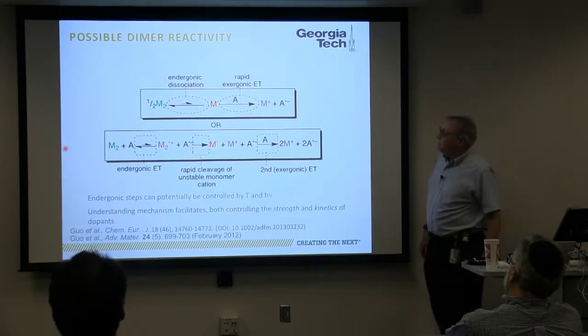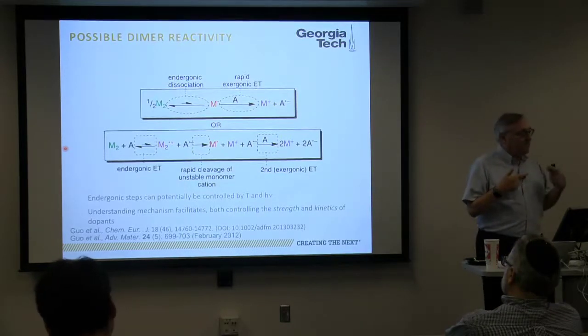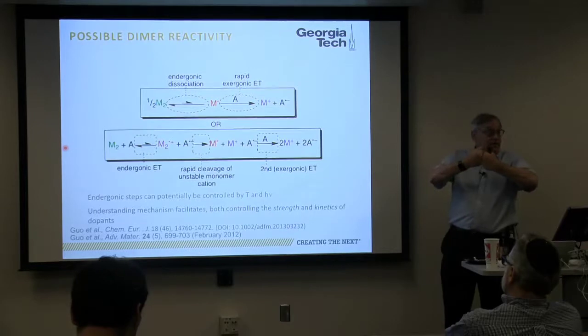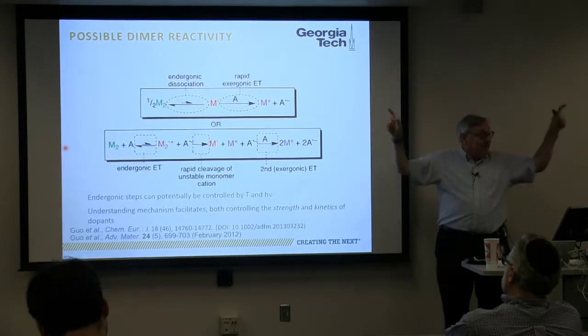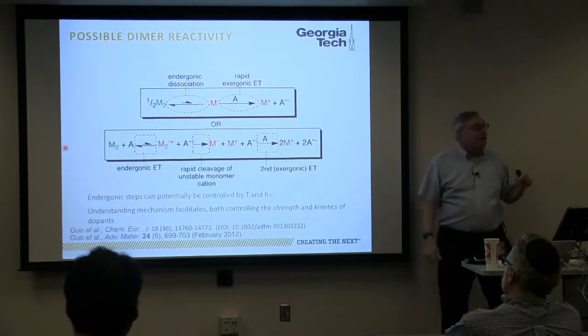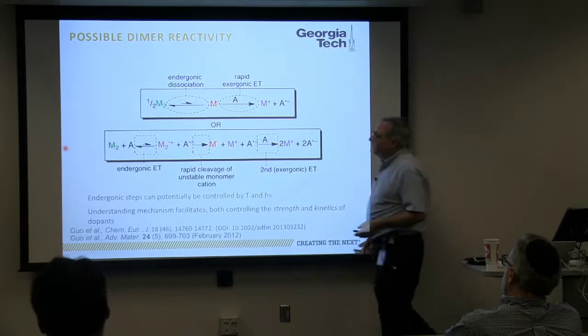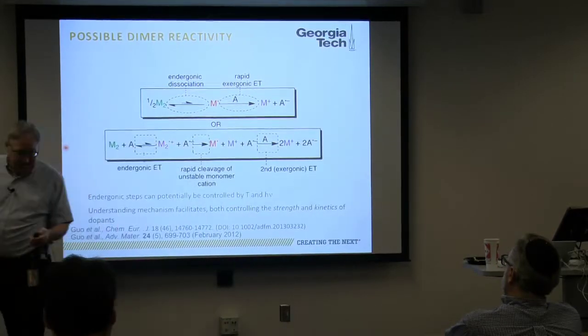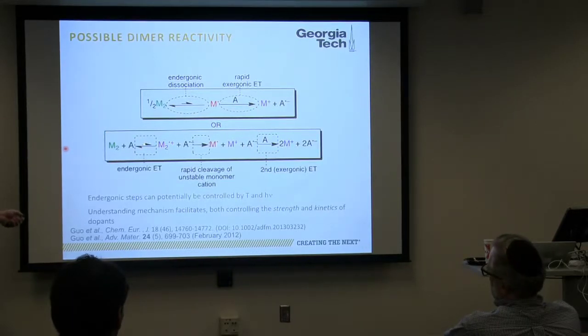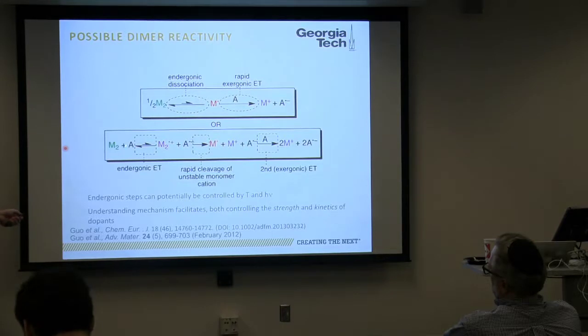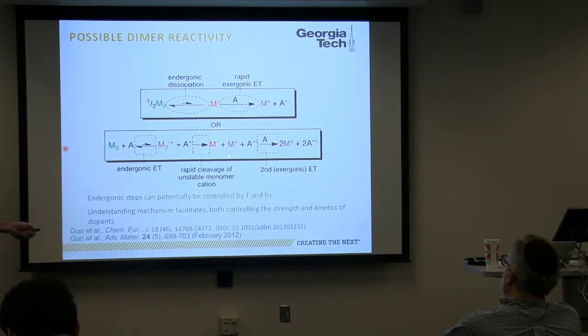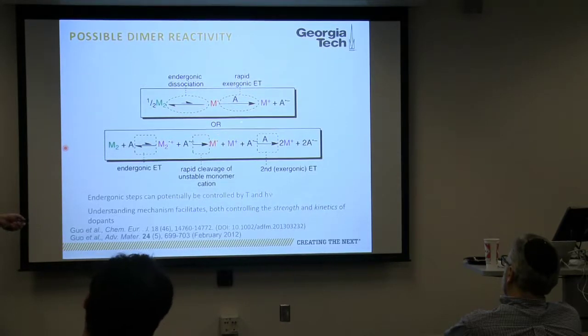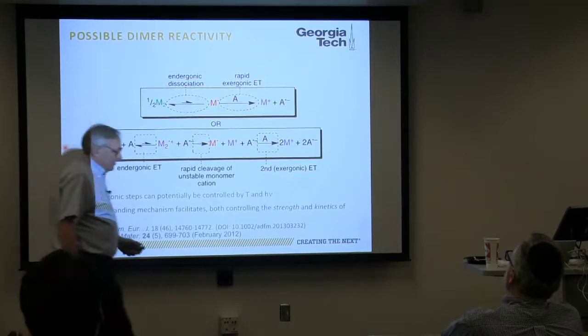So what that showed us is that potentially this class of dimers can react by two different mechanisms. One is the one that we first thought of, where the dimer cleaves and then gives two very reactive materials that transfer electrons. The second one is where the dimer, as was the case in the electrochemical experiment, in a process that may be uphill, transfers one electron to a host. Then you make the cation radical of that dimer, and as I said before, that immediately falls apart to give you a cation and an anion, and now you have that highly reactive odd electron species, which immediately finds another acceptor, and then you get two of these cations and two anions.